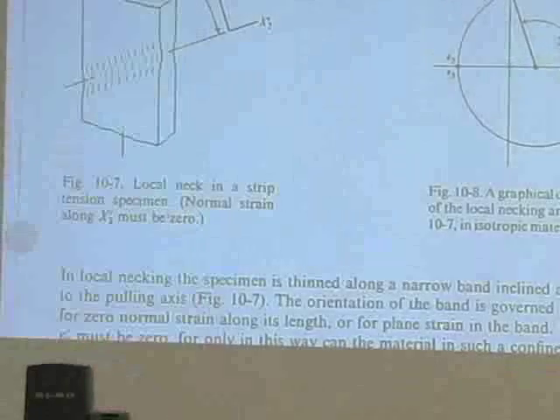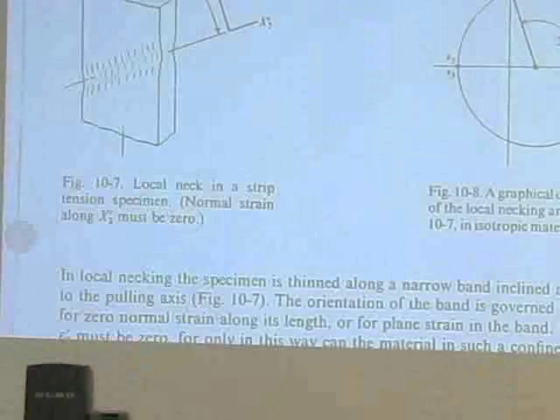And lo and behold, if you go look at these nitrogenated steels, they were finding that. I remember as an undergraduate, I think I got a question on a quiz before they had taught us all this, asking what angle do you expect these? I figured, well, this is the pure shear direction or something, and I said 45 degrees. It's 55 degrees, and if you go measure it, it is 55 degrees, and the way you explain it is in terms of plane strain necking behavior.